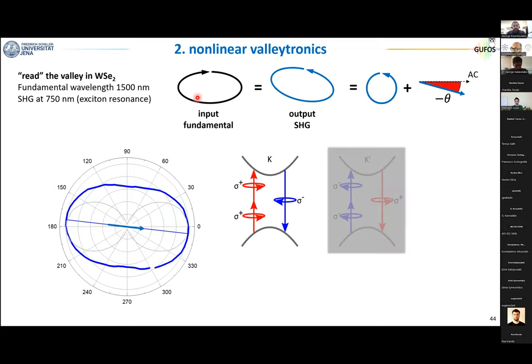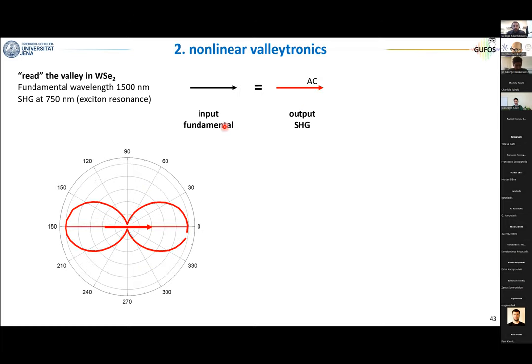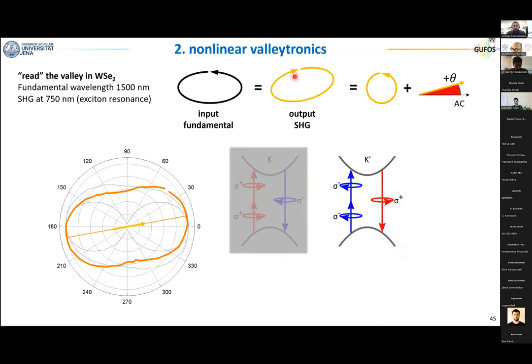Now we go to an elliptical beam, and you see the output is elliptical because the circular input, circular fundamental, turns into circular second harmonic. So this is something that we cannot get rid of, it will always be there. But the interesting part is that the ellipse now is rotated with respect to the input. And this rotation is because the linear component of the ellipse is tilted in one direction. There is an angle minus theta. And interestingly, if we change the direction of this ellipse to the other side, the rotation will be in the opposite direction. And this is a clear indication that with the different circularly polarized light, we excite either K or K prime.